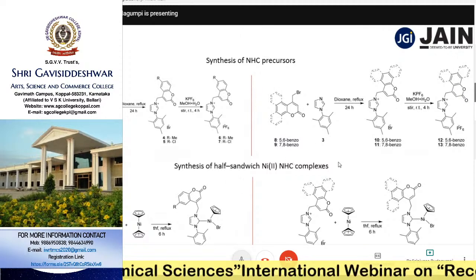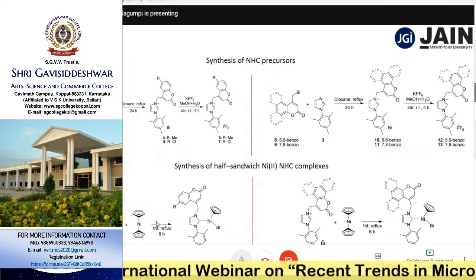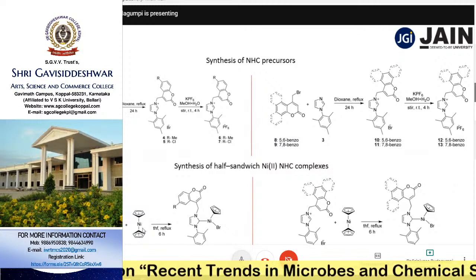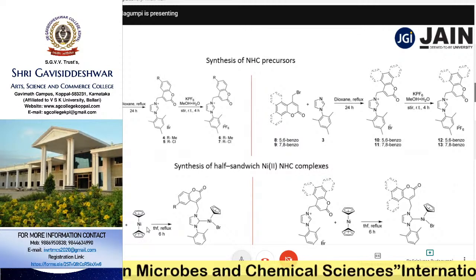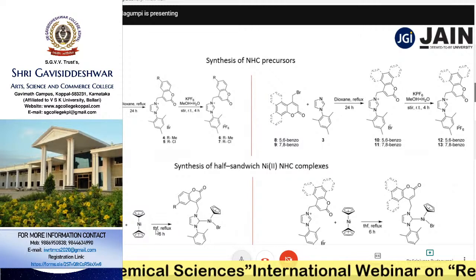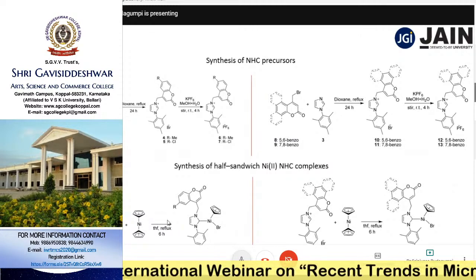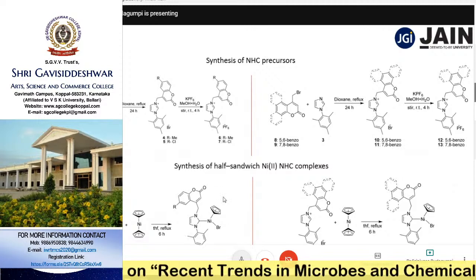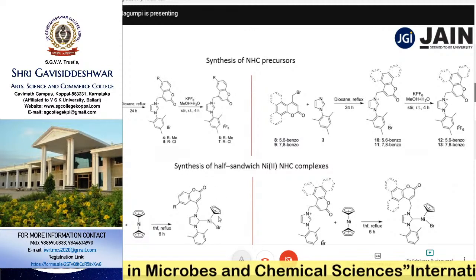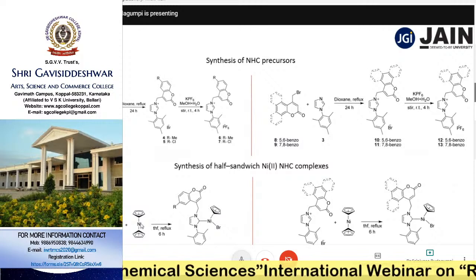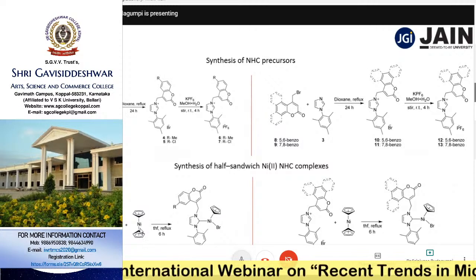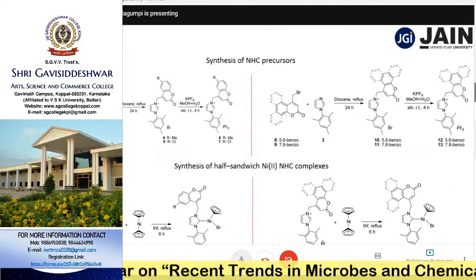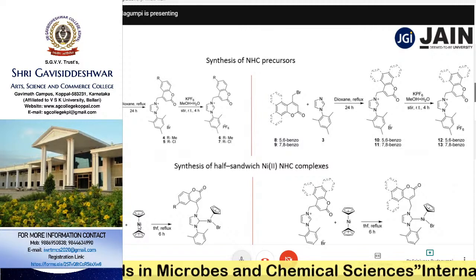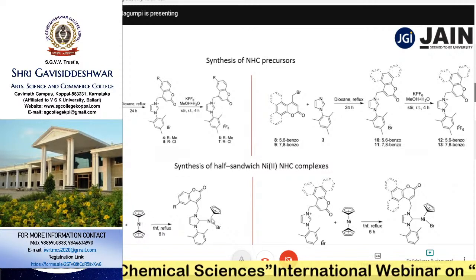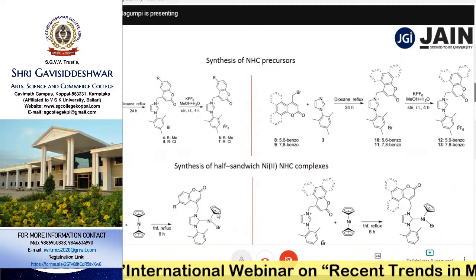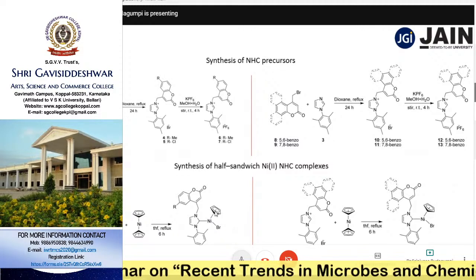Okay. So the complexes are prepared this way: the salt was treated with nickelocene. Nickelocene is just like ferrocene. This nickelocene was treated with this salt in THF under nitrogen atmosphere using the Schlenk technique, in order to get this particular type of complex, which is a half sandwich complex. Ferrocene is a sandwich complex. Even nickelocene is a sandwich complex because nickel is sandwiched between two planar cyclopentadienyl ligands, while here nickel is present with only one Cp ring, hence this is called a half sandwich derivative, right?